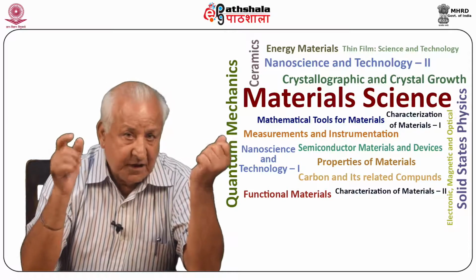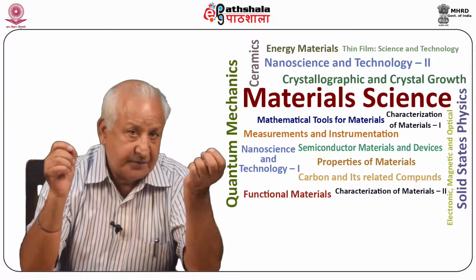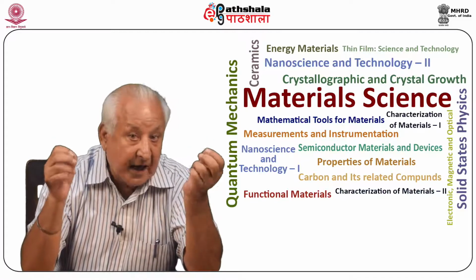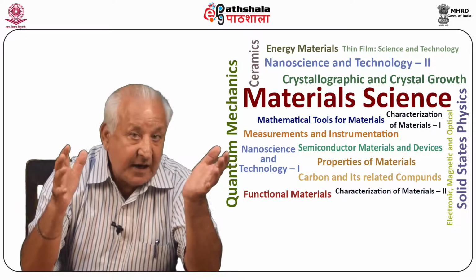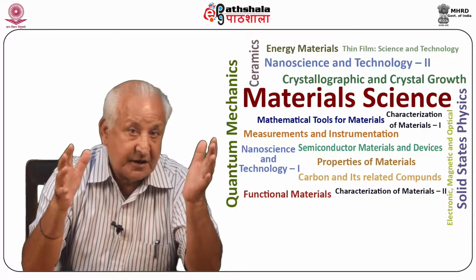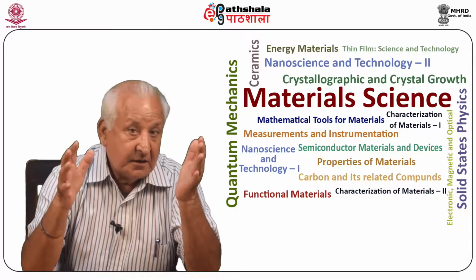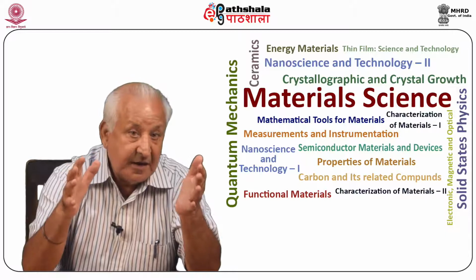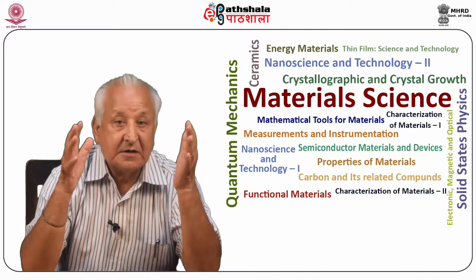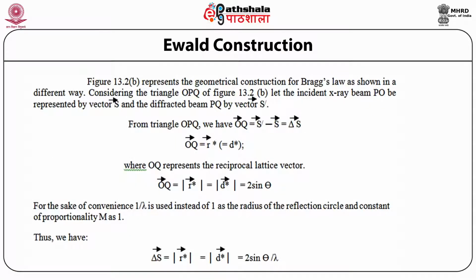This circle is therefore known as the circle of reflection, which, if considered in 3 dimensions, will be substituted by a sphere. The above said construction by Ewald, and the above described sphere of reflection, is named after him as Ewald sphere. Figure 13.2b represents the geometrical construction for Bragg's law shown in a different way. Considering the triangle OPQ of figure 13.2b, let the incident X-ray beam PO be represented by the vector S and the diffracted beam PQ by the vector S prime.